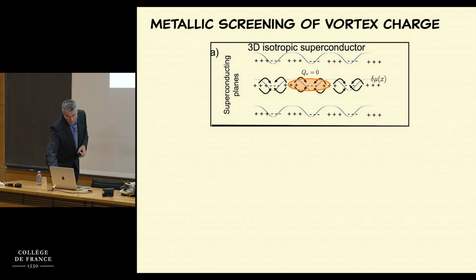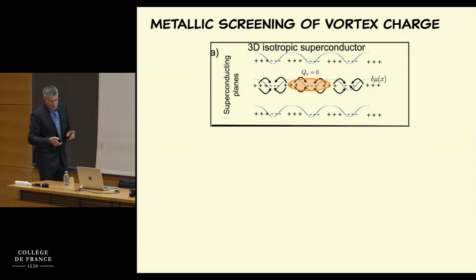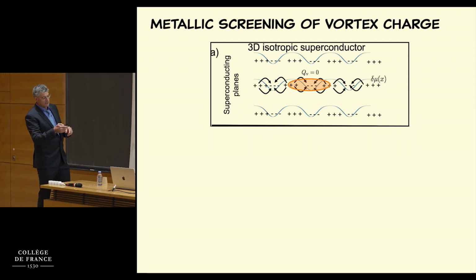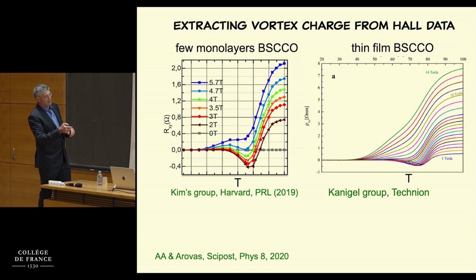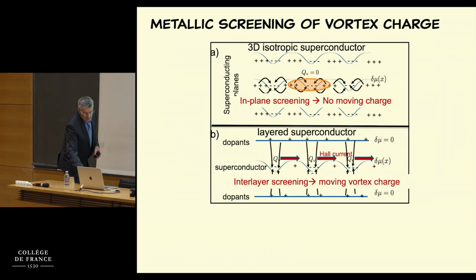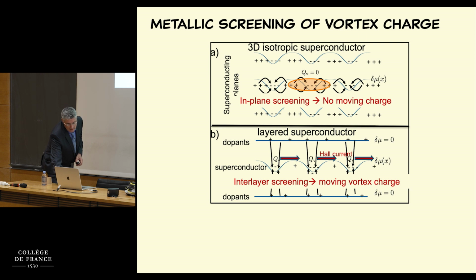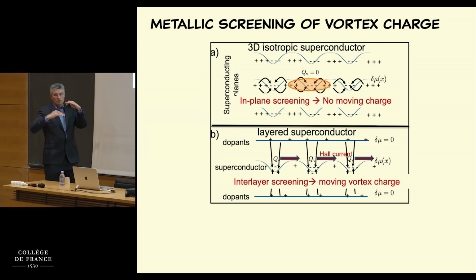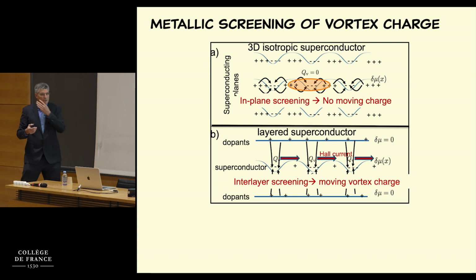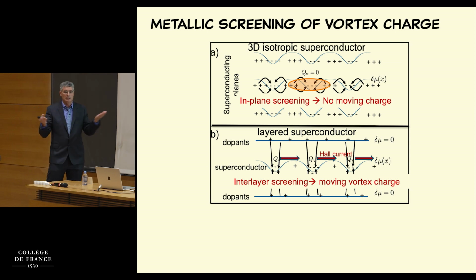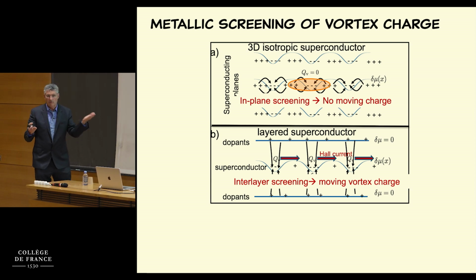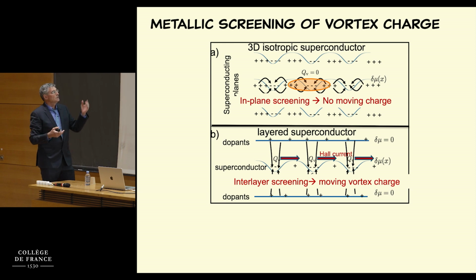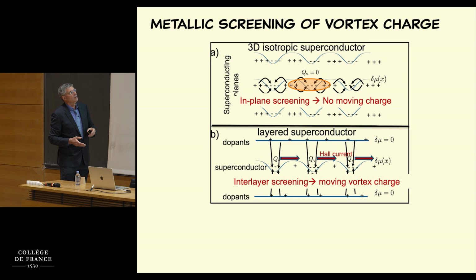Okay, now the charge itself, there's another problem. The charge itself on each layer is completely neutralized within the layer. But if you have a layer and a dopant layer on two sides, or if you have a very thin film and you can push out the charge from the superconducting layer to a third dimension where the charge is parked, it'll be like a semiconductor where the dopants don't live on the same layer as the 2-deg, and then you have currents of electrons where the dopants don't move. So if you get to that situation, then you'll have a Hall current.